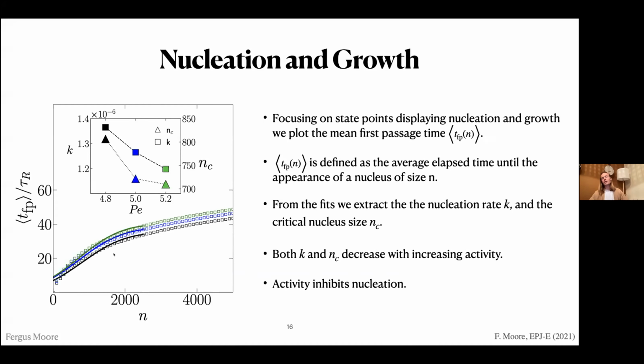People have done a lot of work with the mean first passage time, and there's a fit you can do, which lets you extract the crystal nucleation rate K and the critical nucleus size n_c, and we learned that both parameters decrease with increasing activity, and that tells us that activity inhibits nucleation.